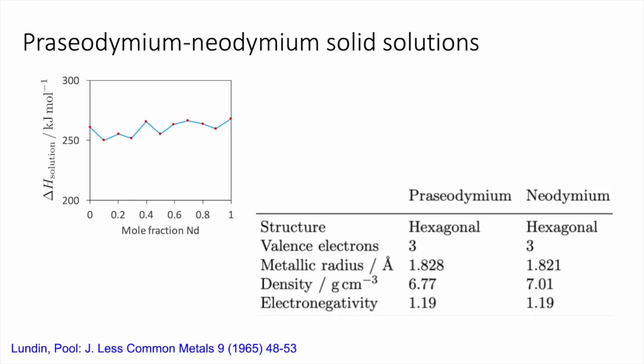Now, there are very, very few ideal solutions in nature. This is an example, praseodymium and neodymium. They form an almost ideal solution because they have the same crystal structure, the same number of valence electrons, their metallic radii are very similar, the density is not that different, and similarly the electronegativity of these atoms is similar. So they have very similar characteristics, and when you mix them, they don't mind which kind of atom is next to them. So they form an almost ideal solution. So, for example, the enthalpy of solution does not change with the mole fraction of neodymium.